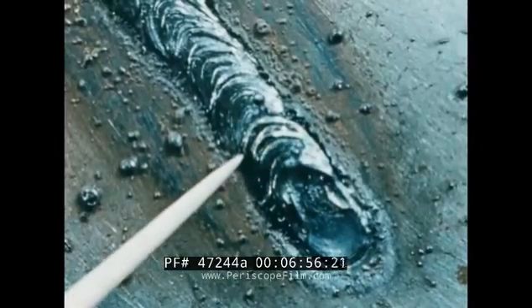If the arc is too long, the metal melts off the electrode in large globules. These globules wobble from side to side and drop on the work in the form of spatter instead of going to the pool as useful weld metal. A wide, spattered, and irregular bead is formed.